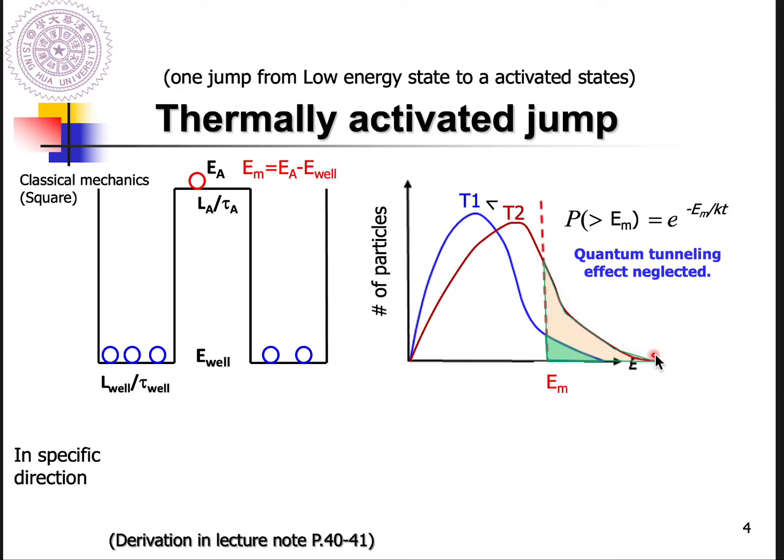then you can observe this curve shift to the right-hand side. And here you can observe that more atoms have sufficient energy to overcome this energy barrier. And the exact portion of atoms we can estimate by this equation is proportional to exponential minus energy EM divided by kT.